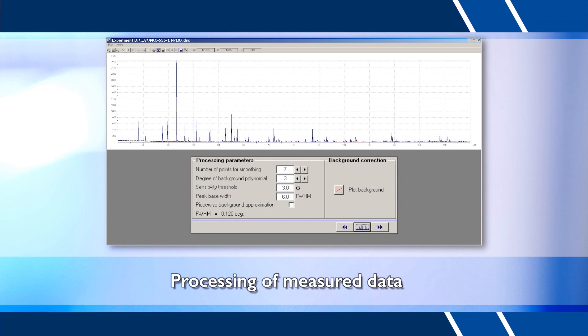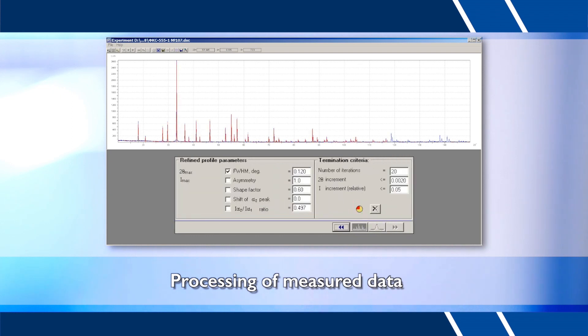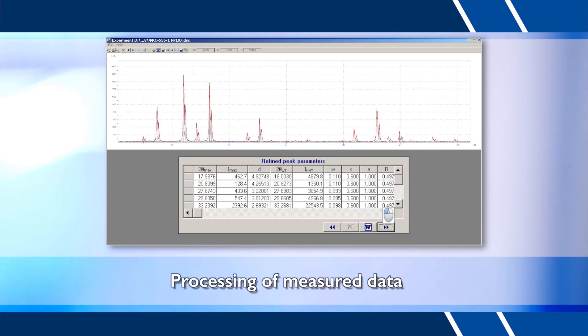Processing of the measured data includes background approximation, peak search, separation of K-alpha duplets, refinement of peak profiles and calculation of their integral and relative intensities.